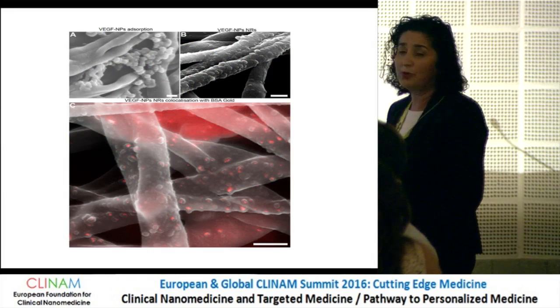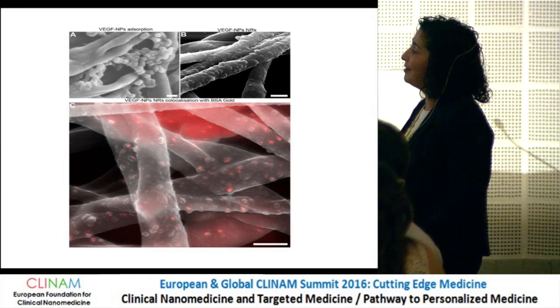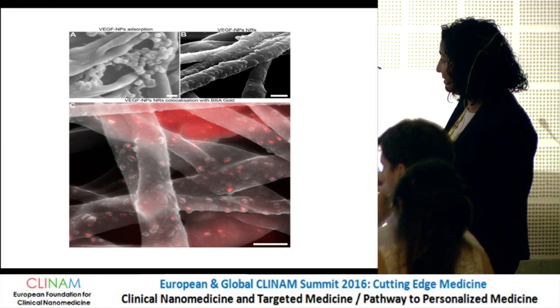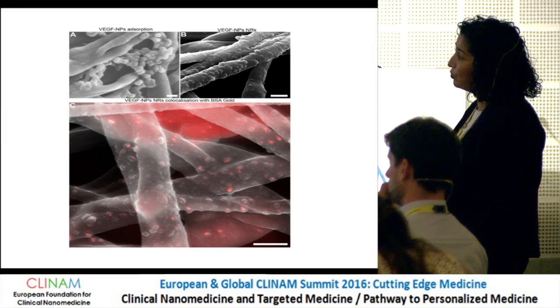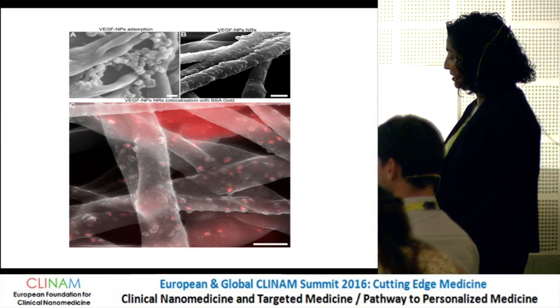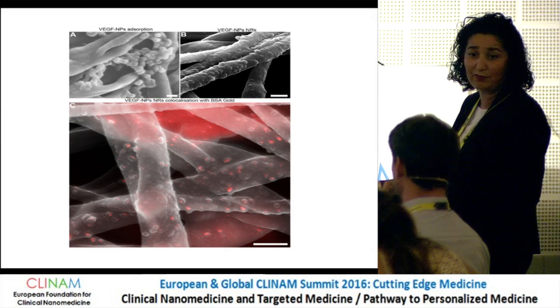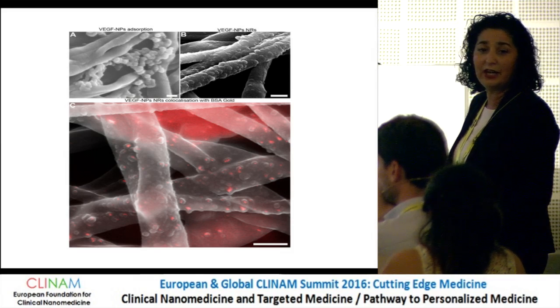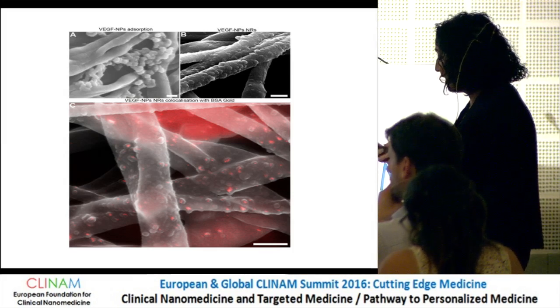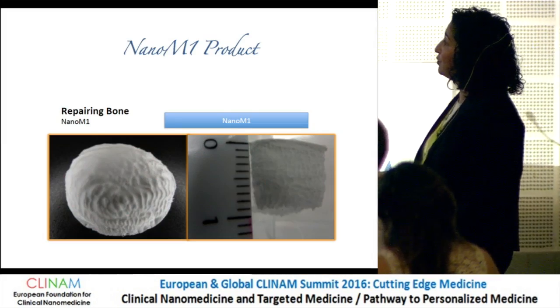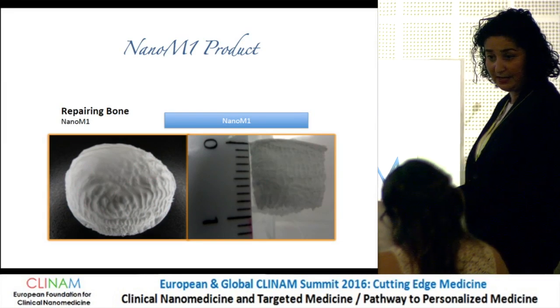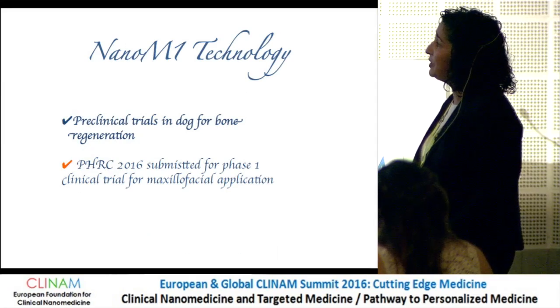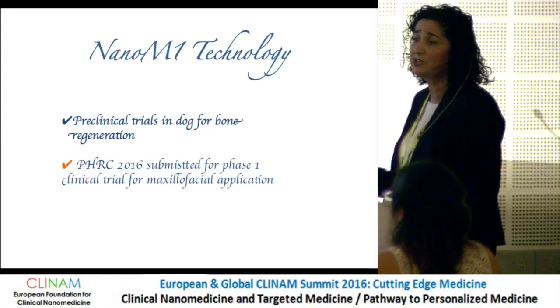We validated this technique by also incorporating nanoparticles made of chitosan with VEGF inside. You can see here the nanofibers with the nanoparticles as a coating — when adding nanoparticles directly there is aggregation, but with the nanoreservoir technology we can incorporate the nanoparticles homogeneously around the nanofibers. This is the first product for bone, manufactured up to one centimeter thick by electrospinning. We conducted a preclinical trial in dogs for bone regeneration in maxillofacial applications.